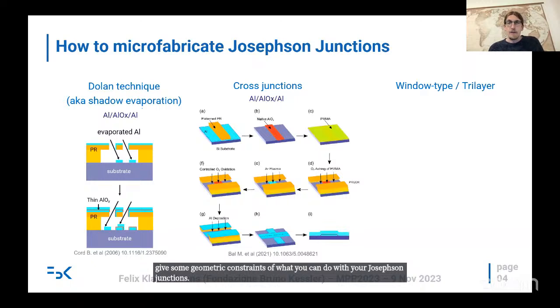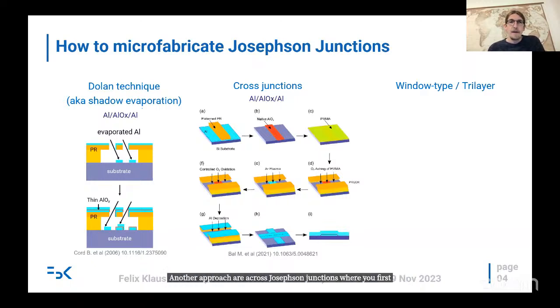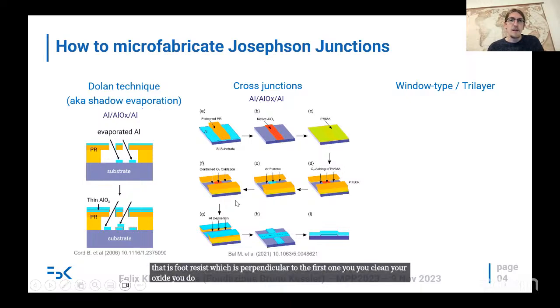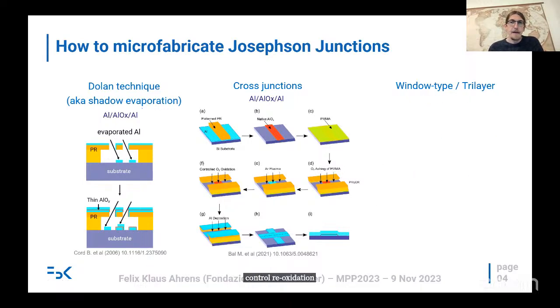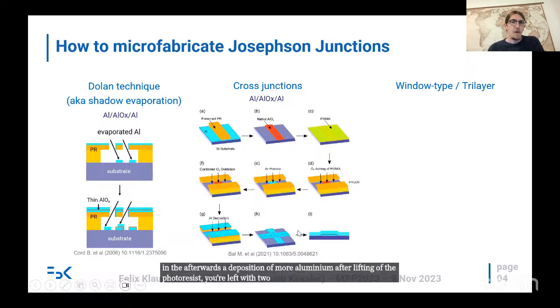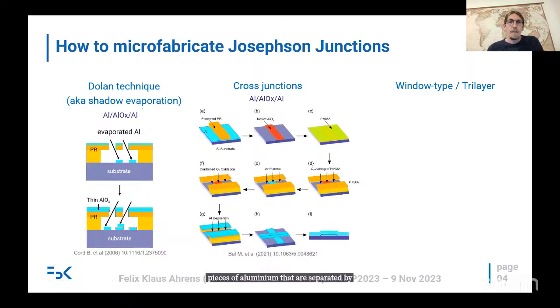Another approach are cross Josephson junctions, where you first pattern one electrode in aluminium. This will oxidize because you break vacuum. You will structure a second layer that is a photoresist, which is perpendicular to the first one. You clean your oxide, you do a controlled reoxidation, and afterwards a deposition of more aluminium. After lifting off the photoresist, you're left with two overlapping pieces of aluminium that are separated by a thin layer of aluminium oxide, and that is again a Josephson junction.